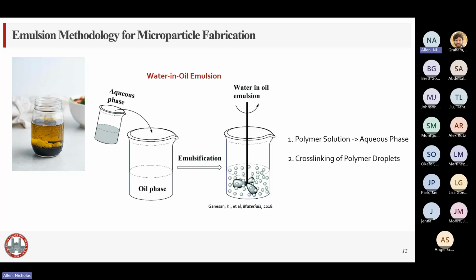And in a water and oil emulsion, biomaterials researchers have been using this to fabricate microparticles. Essentially, they add a polymer solution as the aqueous phase into the oil phase, and then introduce shear and turbulence to the mixture, usually with a stir bar or again a homogenizer. And that breaks that aqueous phase up into micron scale droplets stabilized within the oil. And then they introduce a cross-linking mechanism on the emulsion to stabilize those aqueous droplets into hydrogel microparticles.